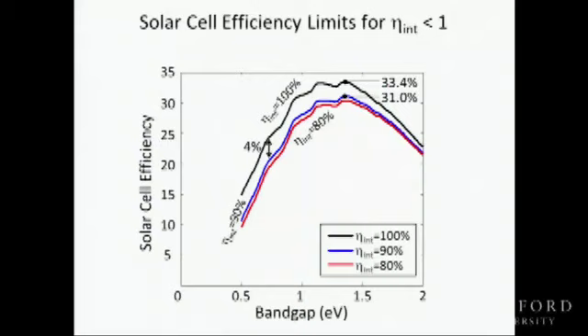I guess this is the main point I wanted to show here: if you go from 100% internal fluorescence yield to 90% to 80%, almost all of the penalty is between 100% and 90%. And going from 90 to 80, the penalty is rather small. Okay, but there's a second purpose in this graph.